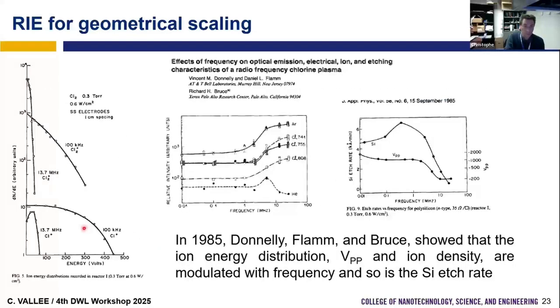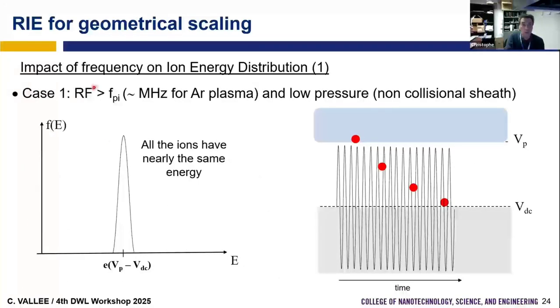So first, for example, we use a 13 megahertz generator. When we use a 13 megahertz generator, usually this frequency is higher than the ion plasma frequency of the ionic species in the plasma. If we don't consider very light ions like hydrogen, the plasma frequency is several megahertz, so it's lower than 13 megahertz.